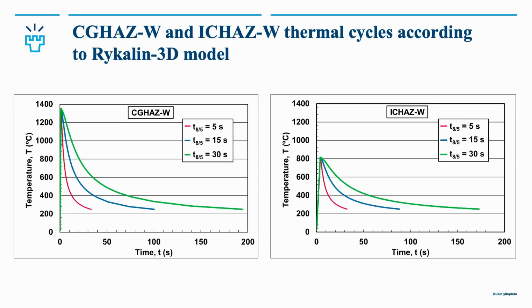And for the thermal cycles that were simulated, we had two different heat affected zones: coarse-grained heat affected zone and intercritical heat affected zone. The peak temperature here was 1350, which means that the steel is fully austenitized at this temperature. While in the intercritical heat affected zone, the peak temperature was 815, which means that it is between AC1 and AC3 temperatures, so it is partly austenitized. And we used three different cooling times, which represent the typical cooling times used in welding this type of steels.